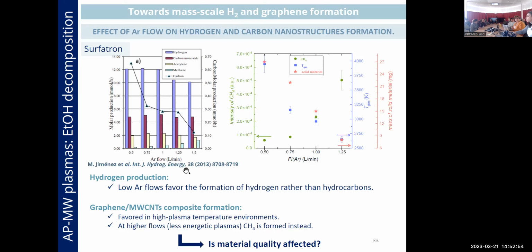Here you have the formation of gaseous byproducts: hydrogen, carbon monoxide, acetylene, and methane. And it's also plotted the amount of material that is produced. You can see that for hydrogen, it seems that the reaction favors the formation of hydrogen for low argon flows. What about the material? We can observe that the amount of material decreases with the flow of argon.